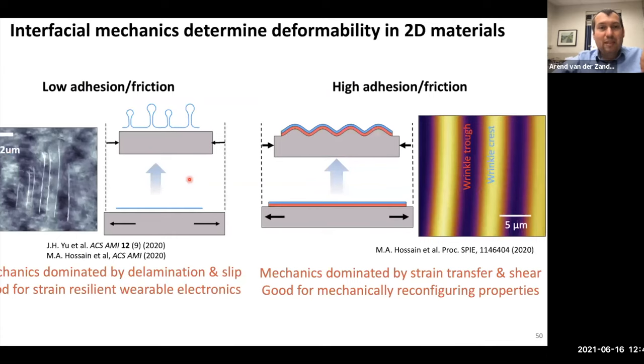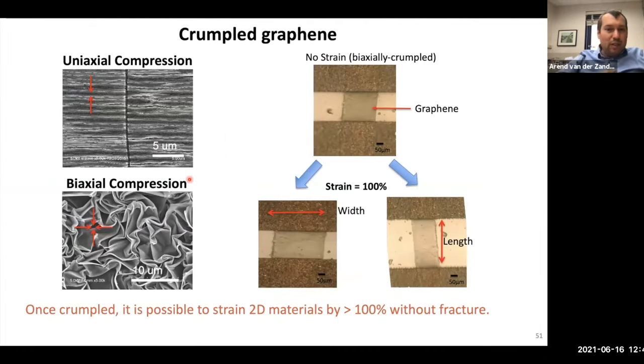And basically what we've learned over time is that a 2D material, if you don't stick it strongly onto the substrate and you produce compressions, it'll delaminate from the surface, which makes all these wrinkle and crumple features. To get a sense for what this looks like, here we have a couple of electron microscopy images. If we take graphene on a surface and apply uniaxial compression, we get all these wrinkles along one direction. If we apply biaxial compression, just like if you take a piece of paper and crumple it up, then you get these fractal structures.